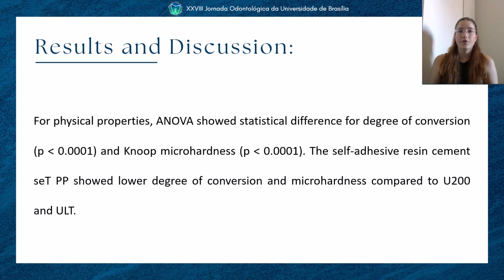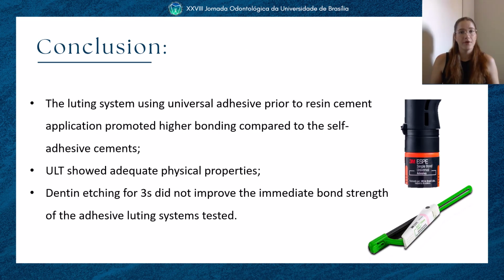For physical properties, ANOVA showed statistical difference for degree of conversion and micro-hardness. The self-adhesive resin cement SeT PP showed lower degree of conversion and micro-hardness compared to U200 and ULT. Therefore, it can be concluded that the luting systems using universal adhesive prior to resin cement application promoted higher bonding compared to self-adhesive cements. Also, ULT showed adequate physical properties.